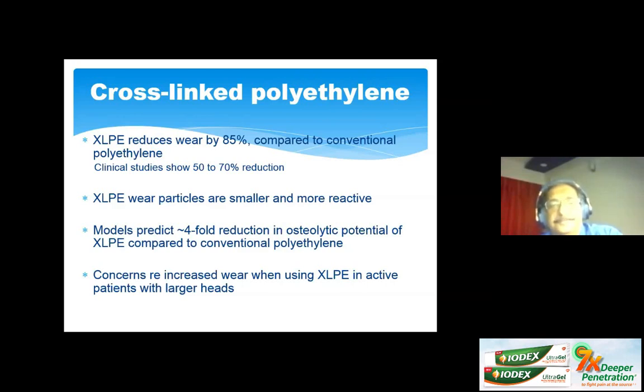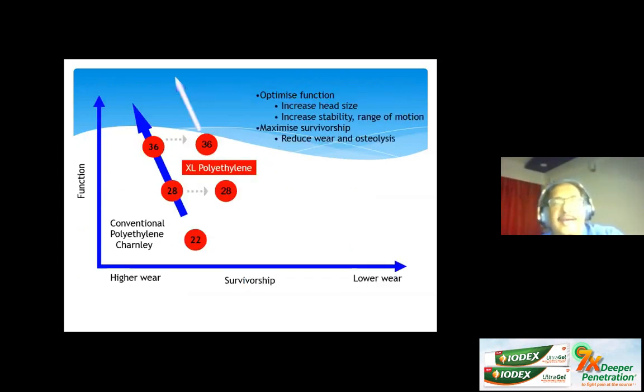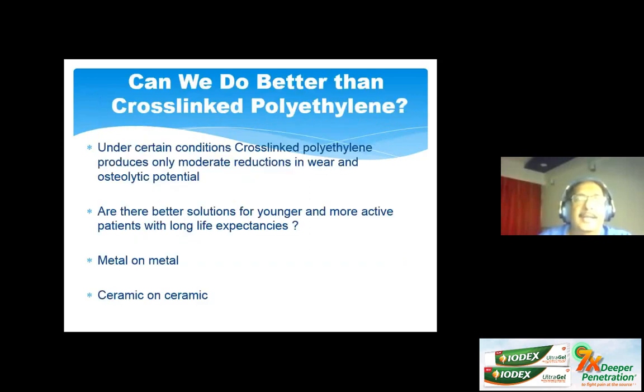So on a conventional scale, we don't tend to go beyond 36, but that is only if you're using ceramic heads. I will come to that in a minute. So this is where we have improved on the Charnley graph, as in we can use bigger heads now with a better quality polyethylene and still expect it to do better than if we were using the same with the conventional polyethylene. So we've improved that aspect of increasing head size and increasing stability.